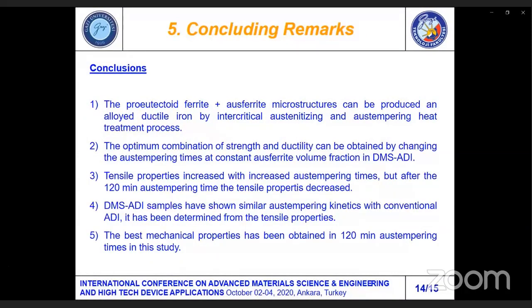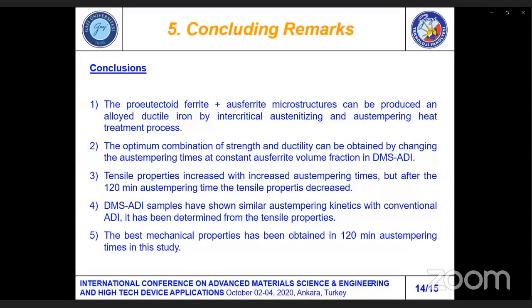And the final conclusion: the proeutectoid ferrite plus ausferrite microstructure can be produced in an alloyed ductile iron by intercritical austenitizing and austempering heat treatment process. The optimum combination of strength and ductility can be obtained by changing austempering times at constant ferrite volume fraction in dual matrix structure austempered ductile iron.